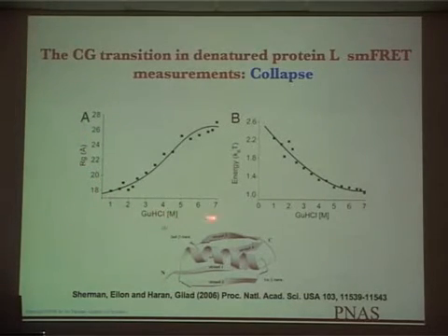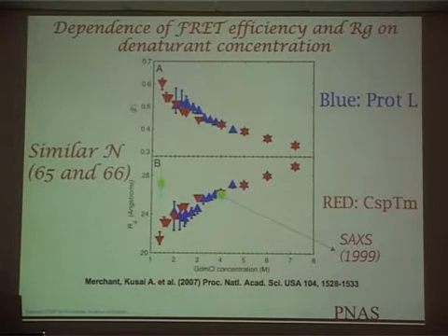Radius of gyration is a function of the guanidinium concentration. And you see this really looks like a continuous transition. The molecule indeed does undergo collapse from an unfolded state of 25 angstroms. At the end, in fact, when you go to 0, it's a little bit less. It's about 16 or something like that. Okay, so this is a collapse transition. And there's some energetics that have actually been pulled out of that. This is another experiment on cold shock protein, very similar to this. And this is from Bill Eaton.